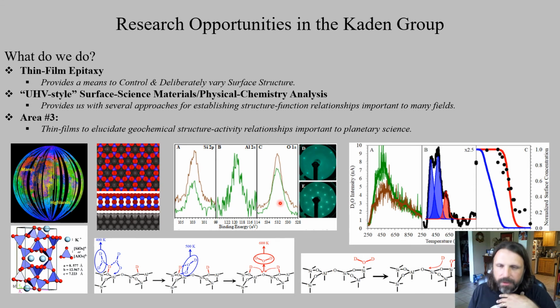Now, long story short of this is, by comparison, what we could do is something called temperature programmed desorption, which uses a mass spectrometer to analyze gases as they leave a sample. So in this case, we would dose a sample with water at low temperature and then observe the water that came back. And that told us something, because we know some of that water would actually cleave and bind as OHs. We were able to learn something by comparison with other literature about the quantity and strength of those OH groups, which are shown here in red.